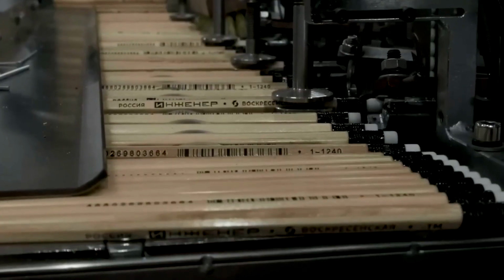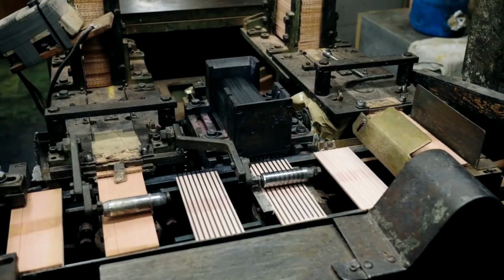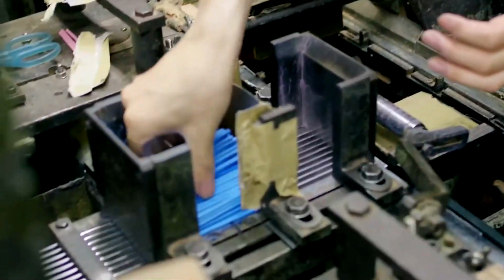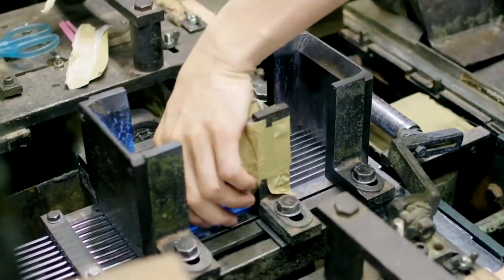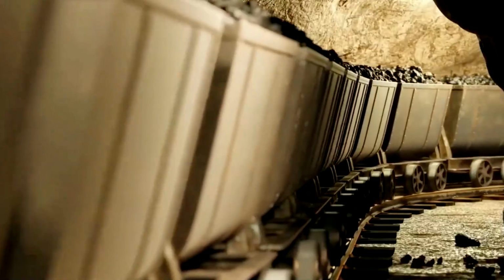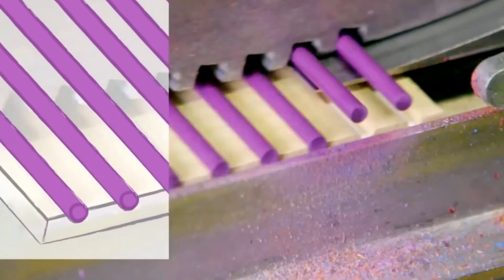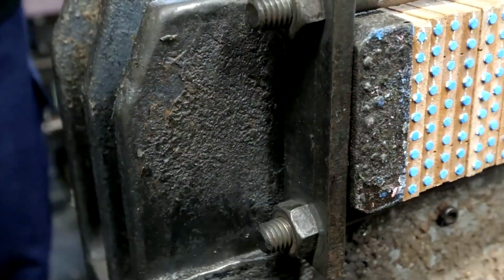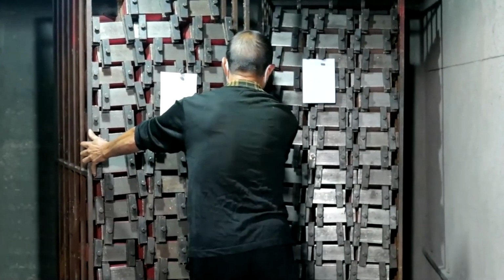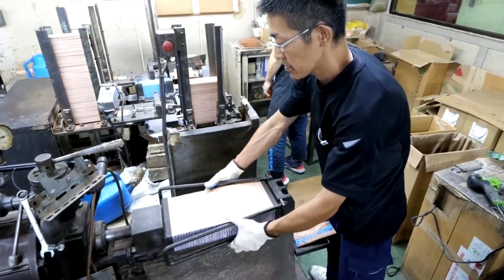Once the ingredients are blended into a uniform paste, the mixture is extruded into thin strands similar in shape to their graphite counterparts. However, it is visible how the process differs here, as colored leads are never fired in kilns. Exposing them to extreme heat would chemically degrade the pigments and alter the color quality. Instead, they are gently dried at lower temperatures to maintain their form, and then cut into standard length segments.